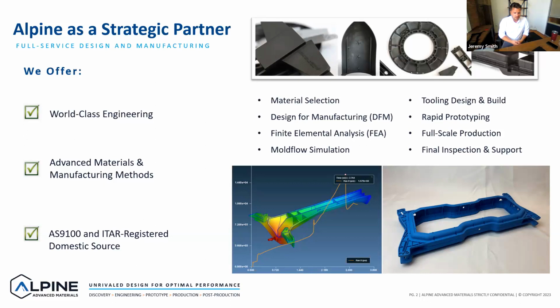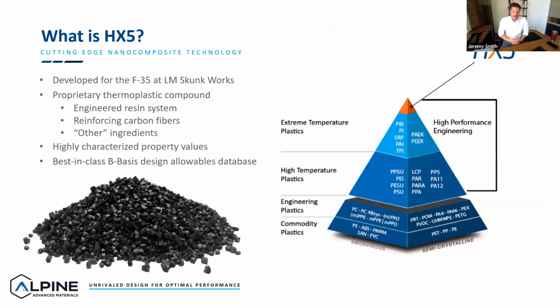But the core focus has been metallic to non-metallic conversion. And one of our novel materials that helps us do that is HX5. It is a proprietary cutting-edge nanocomposite material. It was developed by Lockheed Martin Skunk Works for the F-35. It has since been carved out, and Alpine is the sole proprietor of the material now. It's a unique engineered resin system. It includes reinforced carbon fibers, so there's a carbon-filled material, and then some other ingredients that make it unique that I'll detail coming up.